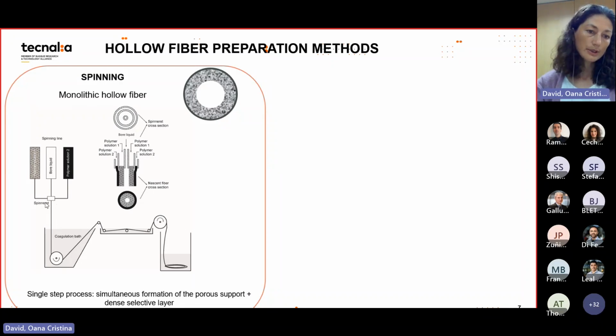And in between, in the air gap, which is here, there is evaporation of the solvent towards the exterior of this nascent fiber, and this promotes the formation of the dense skin outside. And after a few baths and washing, we collect the fibers in wet state. And then we have to dry them to have them for gas separation. So the structure is formed at the same time, and the following step before making the modules is drying of the fibers.